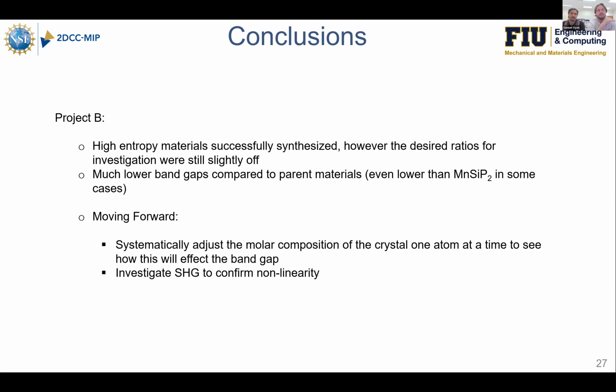And for Project B, we actually were able to get these high entropy materials synthesized. However, the compositional percentages, we weren't able to control as tightly as we had hoped. So we think that attempting to adjust systematically the molar compositions of each of the atoms one at a time might help us to investigate how the band gap changes.